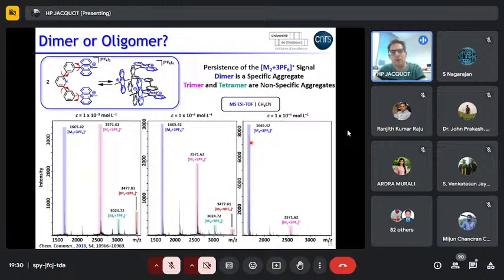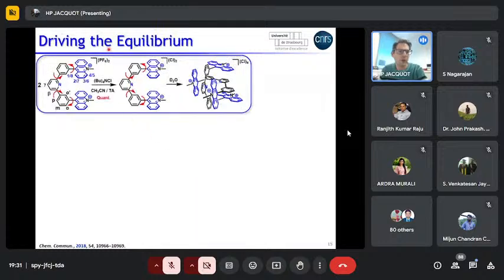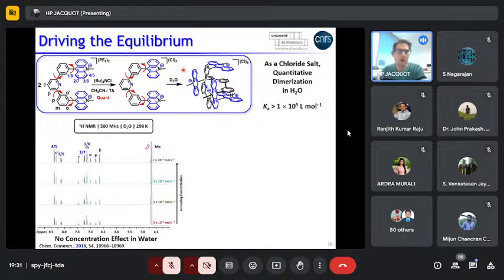Also, what we understand from these studies is that the dimer is not a stabilized species in organic solvents, so it has a tendency to dissociate. So you have to boost the association, and one way is to change solvent. So we converted the PF6 salt into the corresponding chloride salt, then the molecule becomes soluble in water, and what we wanted to do is to use solvophobicity. So indeed, the molecule is soluble in the solvent at different concentrations, actually the same 4 concentrations as previously studied. And we do see only one chemical species, which is the dimer. So thanks to this experiment, we can estimate a binding constant, which is 10 to the 5 molar minus 1, which is a huge gain in comparison to what it was in acetonitrile.